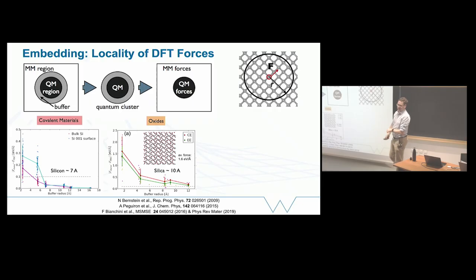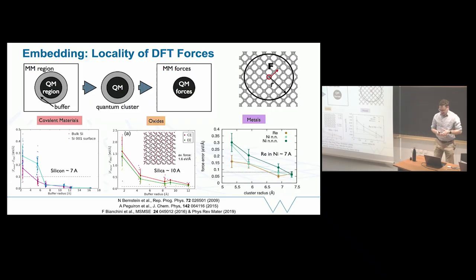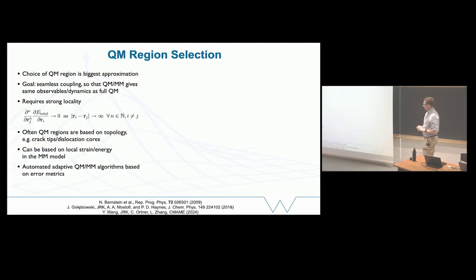So really this approach is not viable in systems with long-range electrostatics. Those remain challenging for machine learning interatomic potentials for exactly the same reasons. Those rely on the same locality assumptions. Metals, again, it's much better because of physical screening processes, so 6 or 7 angstrom, and you have forces which are quite accurate, so the approach works well.